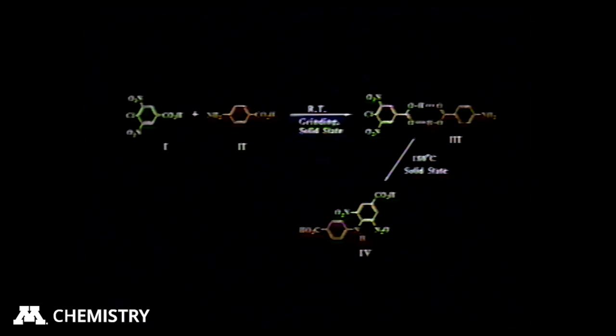So what we have here is a series of solid-state reactions. We're going to start with two different carboxylic acids. One of them has an amine group, that's para-aminobenzoic acid. The other acid reagent has two nitro groups and a para-chloro group, and that para-chloro group is activated by those nitro groups. The first thing we do is simply grind those two acids together, and when we do that, we get a new co-crystal, just like the reactions I showed you just a minute ago.